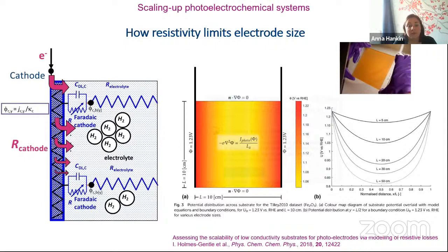by us during a project, and also by my colleague, Isaac, who essentially modeled what happens when you use a 10 by 10 piece of fluorine-doped tin oxide as the substrate for an electrode. And he showed that if you apply, for example, 1.23 volts either side of the electrode, you still have a really big voltage drop as you go into the depth of the electrode. So what does that mean? It means that all the current will flow through the outer parts of the electrode and not very much through the middle. So what's the point of scaling it up?